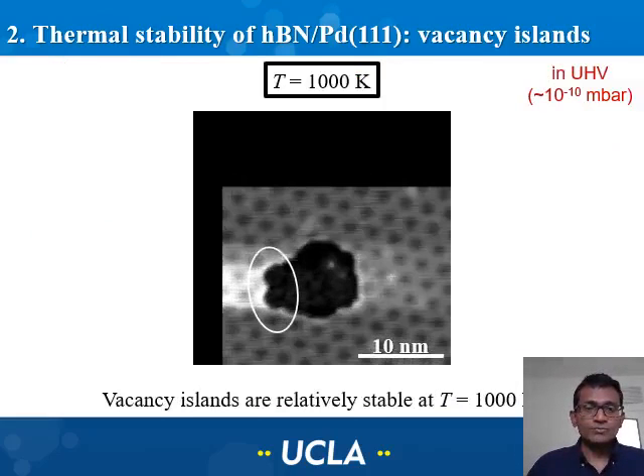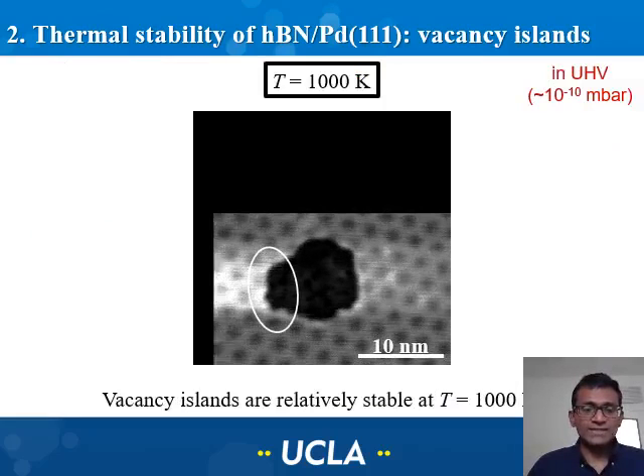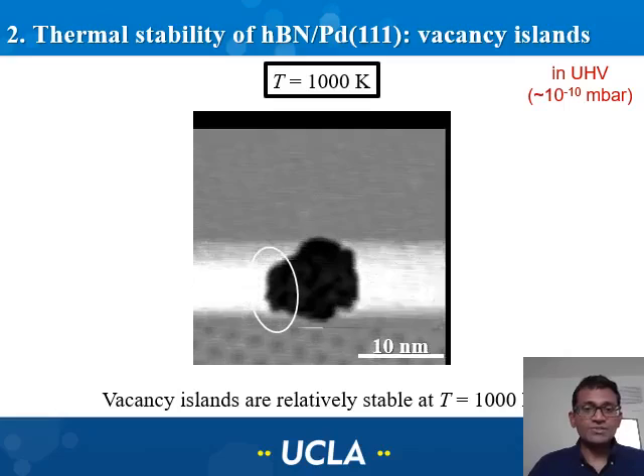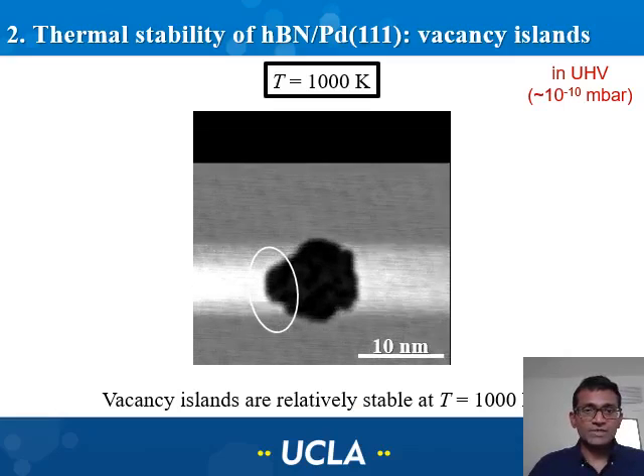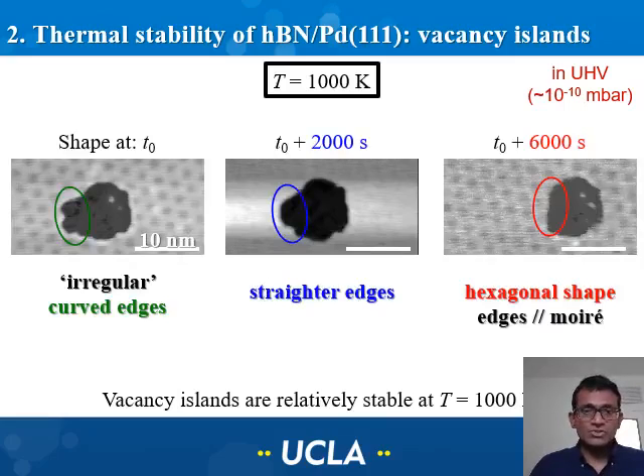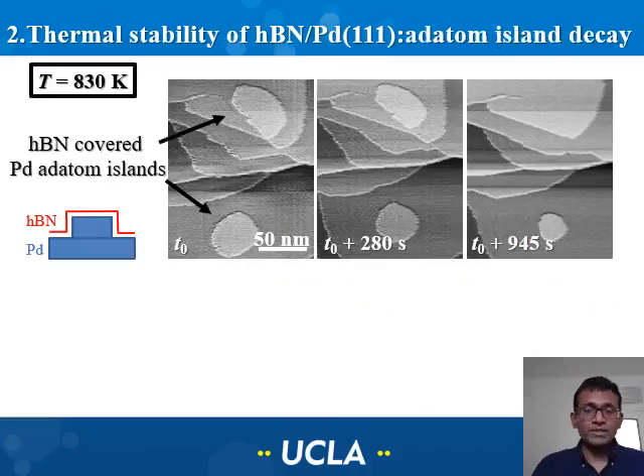And you have seen this video before, but I want to highlight this in higher magnification. So this is the vacancy island that was being annealed, and this is roughly about 10 nanometers in size. And what you have seen in the time-lapse images is that there are little changes to its size or shape. And this is done over 6,000 seconds, and all we observe is small changes in the shape, and the smaller corrugations in the initial shape of the island get a little bit smoothened out. Nevertheless, the island remains the same. And I'll point out why that is important in a couple of slides.